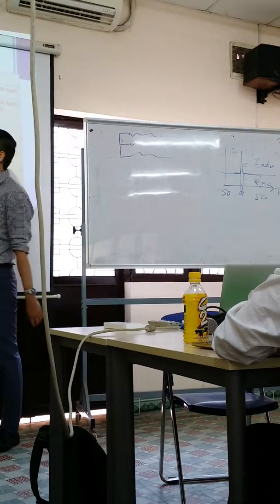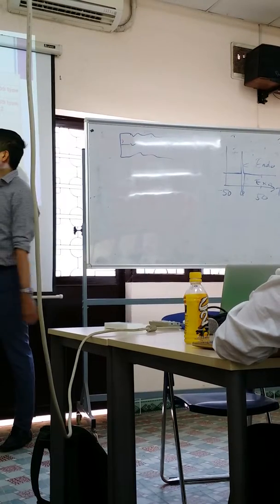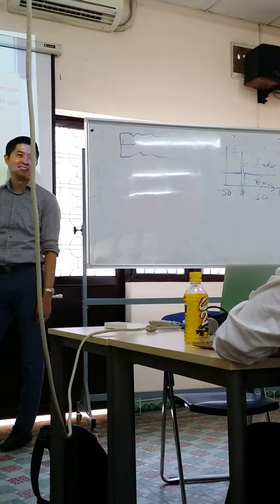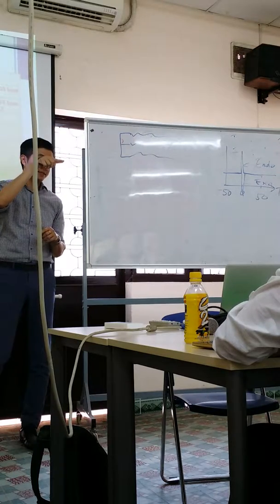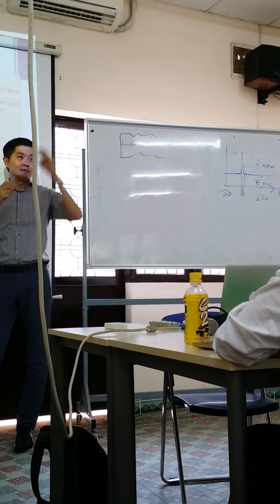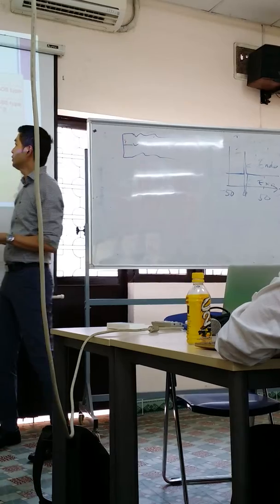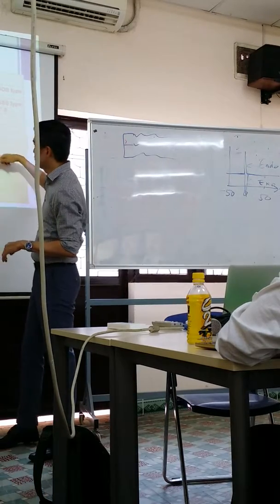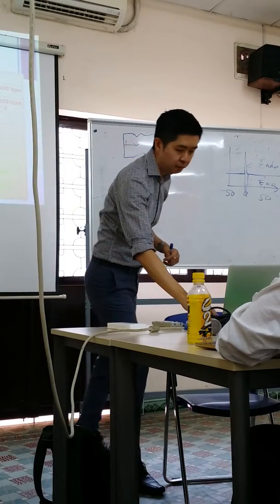Fully hydrogenated oil, the fat crystal is beta 2. Milk fat, beta prime 2. The 2 is referring to 2x. Okay? The 3 is referring to 3x. Alright? So then you have different types in general. Okay?